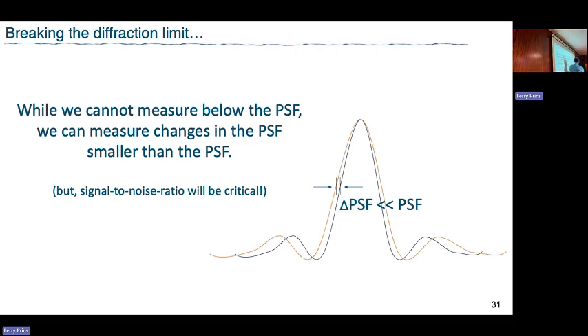So I talked to you about the point spread function, right? The point spread function is my 250 nanometers. That is the highest resolution that I can do. So what I can do is create with a laser a population of carriers that is at the diffraction limit, 250 nanometers. I cannot measure below that, and I cannot generate a population that is smaller than that with my normal optics. What I can do, though, is that when that population starts moving in time, that population becomes broader because they're diffusing outwards, and I can measure the point spread function at a different point in time. And that point spread function is going to be bigger than the original. And I can measure the difference between the population at time 0 and the population at time x with a resolution that is below the diffraction limit.